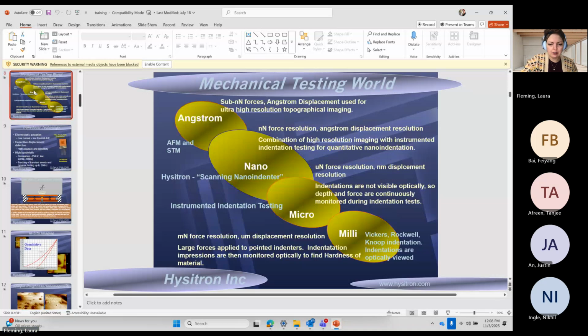There's often a question of where do we fall in material testing. On one end of the spectrum, you've got milli indenters, which require large force resolution and large displacement resolution, meaning you're not going to get as fine detail as you would with smaller ones. This requires you to be able to optically see the indent after you've done it so that you can measure it to make those calculations for hardness and modulus. One step up from that is micro, which has micronewton force resolution and nanometer displacement resolution. And what that means is that we don't have to optically resolve the indent in order to make those measurements.